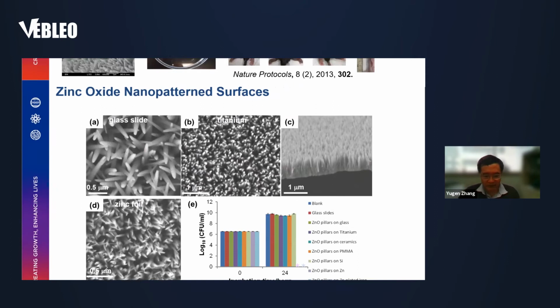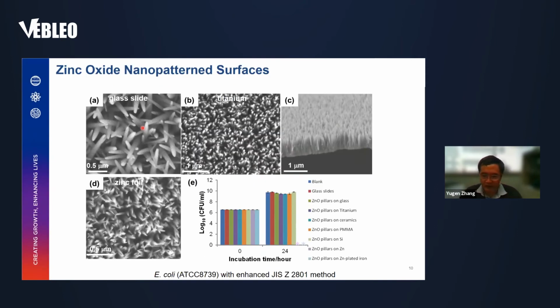And other than this ZIF, we also try looking for more durable and stronger nanostructured materials. And showing here is the zinc oxide nanopattern. We grow these zinc oxide nanopatterns on different types of surface, on glass, on titanium, and also on zinc foils and some others. When we do this antimicrobial evaluation using the JIS Z 2801 measure, we found that these nanopillars on surfaces like glass, titanium, ceramics, PMMA, silicon have no killing. But on the zinc and zinc plated iron have excellent killing.